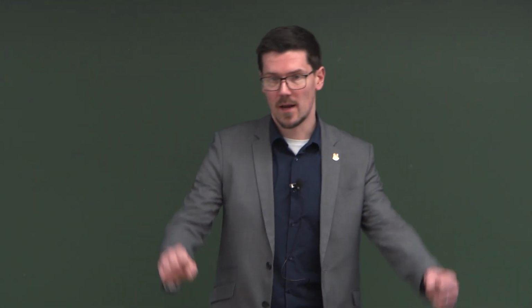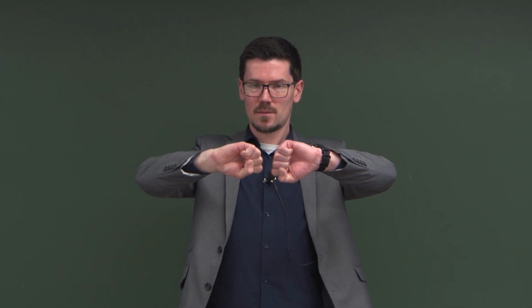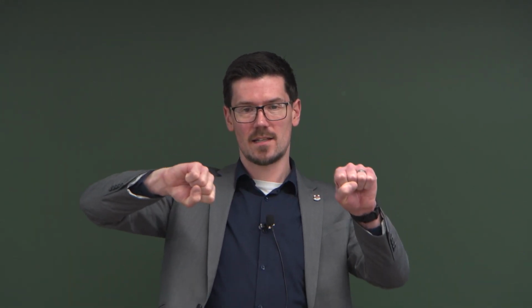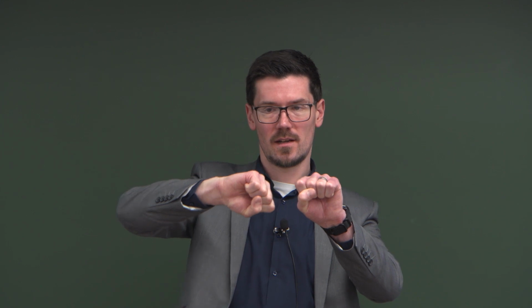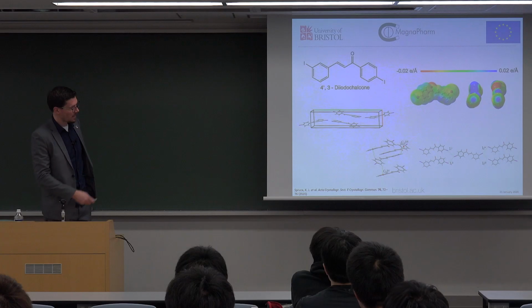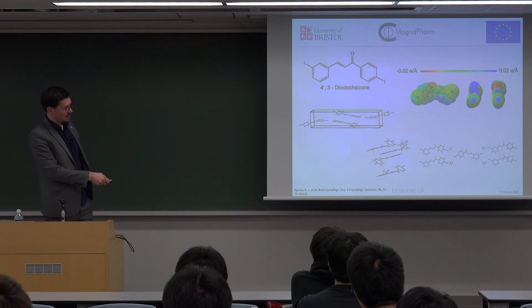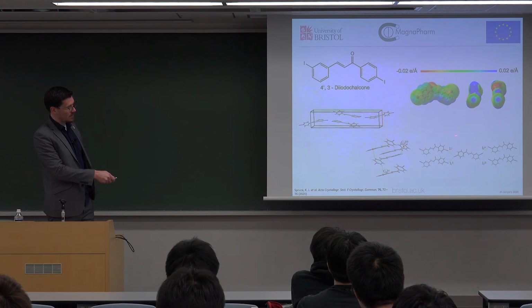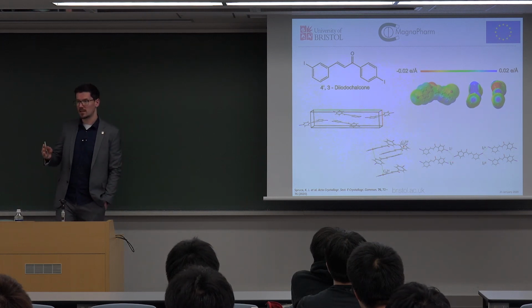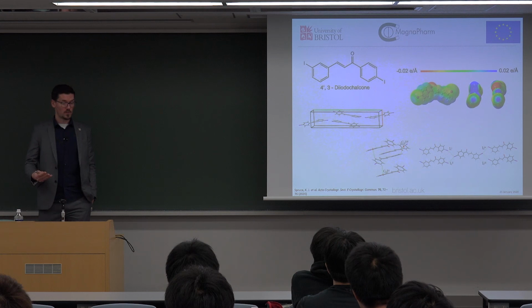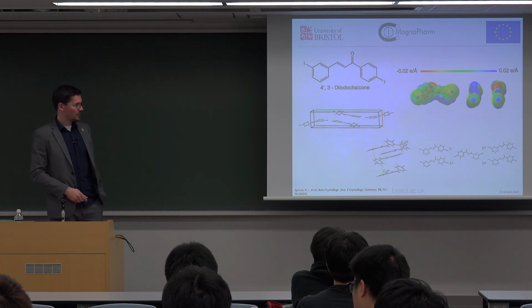So we don't have the iodines interacting like this, because that's positive and that's positive. What ends up happening is we have this kind of interaction, and that's called a halogen bond. And we have those here, these halogen bonds that go all the way through the crystal and make these nice iodine channels, which we think might be interesting for conductivity.